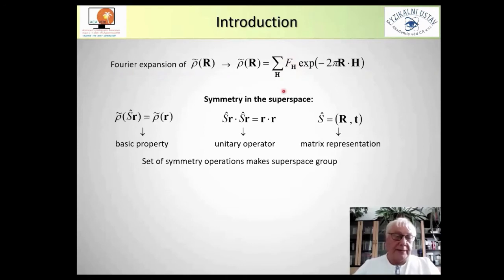Symmetry in the superspace is defined by its basic property: generalized density is invariant with respect to symmetry operations. Symmetry operations are supposed to preserve distances in superspace, and then we can make a matrix representation of this symmetry operation, where this R is now a 3+d by 3+d matrix instead of 3 by 3, and the translation is a vector with 3+d coefficients. This means that we now have a set of operations, and this set of symmetry operations makes the so-called superspace group.